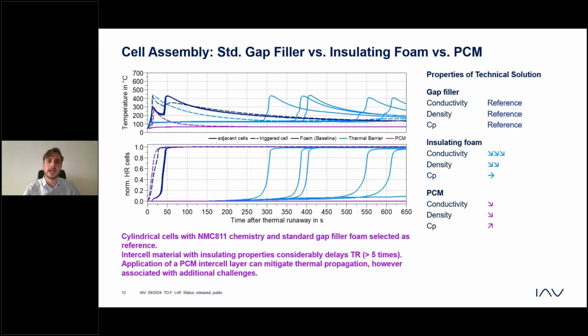Further on, we have been looking at some other kinds of materials. We have been looking not in the experiment, but predictively in the CFD. What we have here is our reference case, which is a reference gap filler. We see we have right now in different EVs, and we have tested it for the thermal runaway. These are the dark blue curves, and the dashed curve is always the central cell, and the straight curve the neighboring cells. We can see that right after the central cell is seeing the thermal runaway, we have the propagation to the neighboring cells.